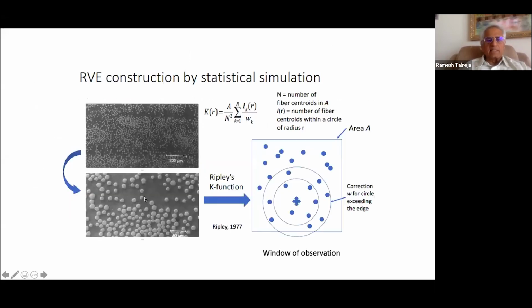So I'll discuss that. So here's an example of, say, you're looking at a cross-section of a UD composite. A bigger picture here shows that there's a lot of non-uniformity. You do a close-up and you see those aspects that I'm talking about, clustering of fibers and resin-rich pockets. So how do we quantify that? It has turned out that some work Ripley did back in 1977 is very useful here. He produced a so-called K function, because he called it K. Formula is here, and I'll talk about that in the next slide.